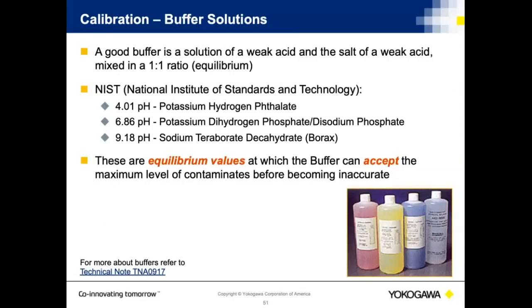Buffers. Buffers are not all equal. NIST traceable buffers are what the Yokogawa analyzers come to you pre-programmed and are expecting to see. And their values at 25 degrees C are 4.01 pH, 6.86 pH, and 9.18 pH. Now, if you use 4, 7, and 10s, that's fine. You just have to make certain that you change the calibration tables inside of your analyzer when you receive it.